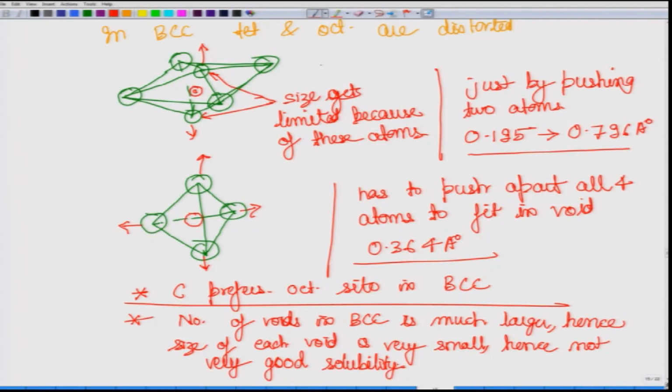So, this helps us understand the interstitial impurity point defects. So, you can see that there is so much intricacy involved in understanding a simple point defect, which in this particular case is the interstitials. So, you have a more open structure like BCC and still the carbon is more soluble in FCC. You have a larger tetrahedral void, but carbon atom prefers to sit in the octahedral void.